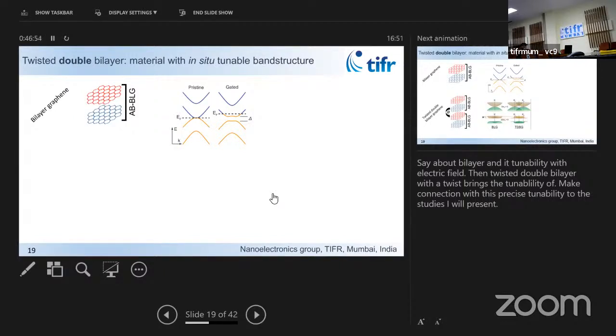If I take 2 layers of graphene like this, and I make a device, and I apply a perpendicular electric field, just put it in between 2 electrodes, the moment I apply electric field, I break a symmetry inside the lattice. I break what I told you is the inversion symmetry, because effectively the cross section of a bilayer graphene will look like this, with an atom here. In the absence of electric field, if you do inversion, this is all carbon. You go back to the same lattice. But the moment you apply a vertical electric field, the potential here and the potential here is not the same. You break inversion symmetry, and that basically produces a band gap.